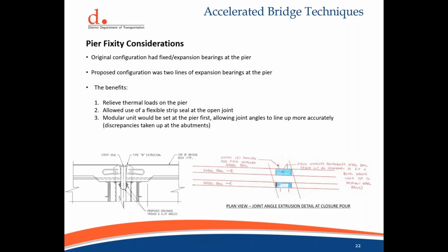We did have some flexibility in installation due to the strip seal and trough material, which was a little bit more lenient, so it helped with the overall fit and alignment of the units across the pier. As I mentioned, the units were first set at the pier, which allowed the joint rails to more accurately line up. And as I said, all discrepancies would be taken up at the fixed abutment.